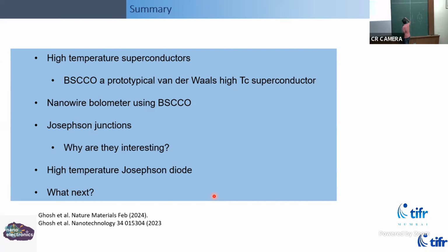So you're worried about, if I have some junction like this, the current here flows in plane, but here it has to go perpendicular to the c-axis. So you're worried about the current changing, or what was your concern? So you showed a graph where you varied the twist angle from 45 degrees to like 22 degrees and so on. So why did you do that?